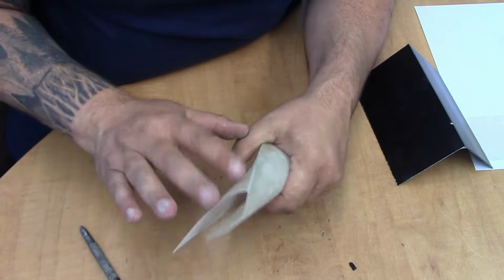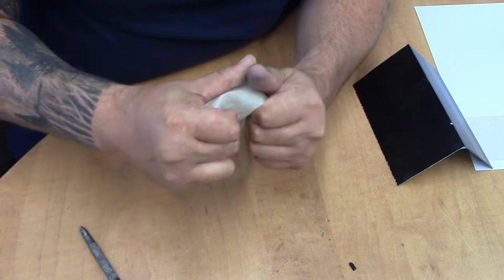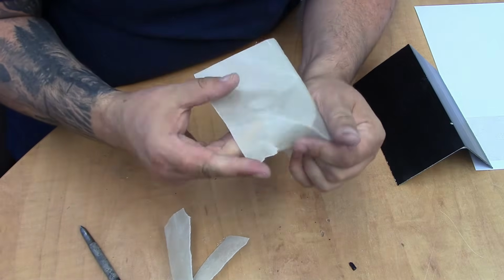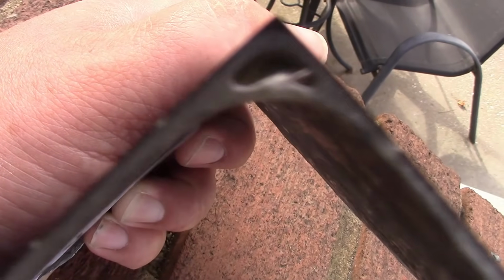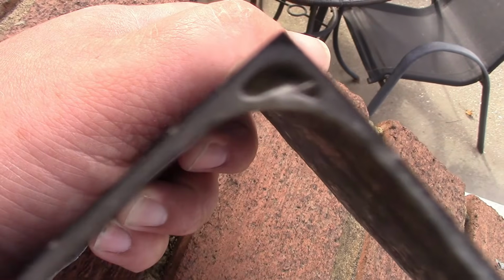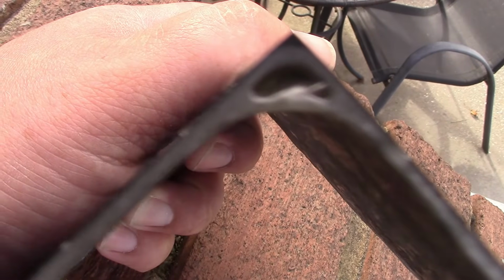In fact, if we take a sample of tissue that's been laid up with resin, it can be easily damaged and actually torn like paper. Our sample looks great when first removed from the mould, but if we cut through the panel, you can see this void between the tissue and fiberglass matting.